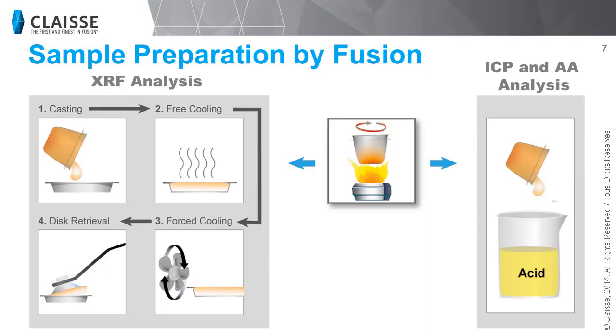For peroxide fusion, once the sample has reacted with the peroxide in the zirconium or nickel crucible, the mixture is dissolved using ultrapure water. Diluted acid is then added volumetrically to get the same acid concentration as used on the ICP.